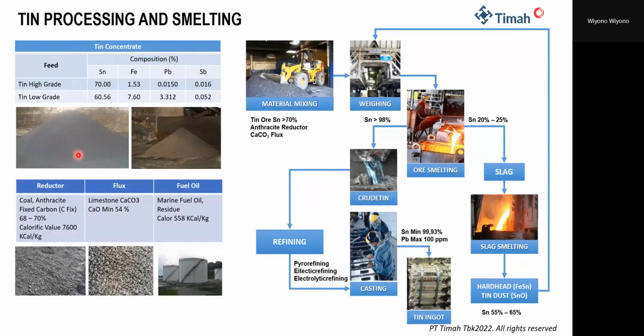Before we smelt, we do some preparation. For example, adding the additional materials that I explained on the previous slide. The first is the reductor. We use anthracite as a reductor. The anthracite has fixed carbon of 68 to 70%. This is a picture of the reductor and flux. The flux that we use is limestone with CaO minimum 54%.